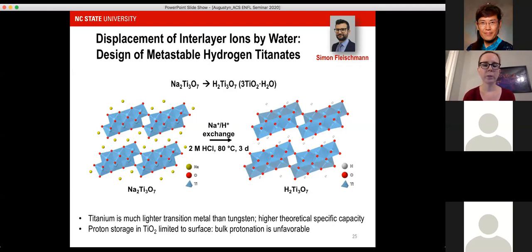So we started to zoom in on these sodium titanates that can undergo proton exchange to form hydrogen titanates. So now we're not talking about water molecules in the interlayer, but what we called structural protons. So the exchange of the sodiums by protons forms the hydrogen titanates. And one thing to note is that when it comes to proton insertion in TiO2, that's limited to the surface. So you need to nanostructure the material significantly to see any sort of significant capacity for proton insertion. The bulk protonation is unfavorable from a structural standpoint.